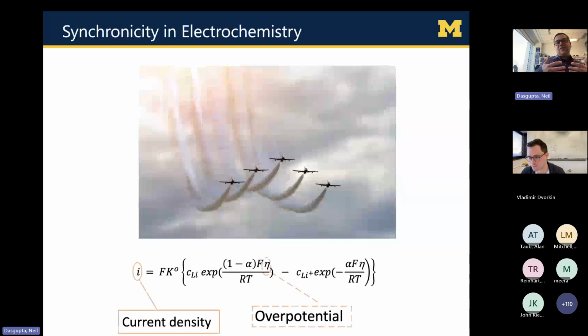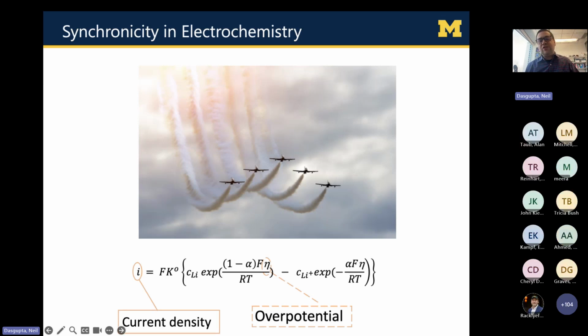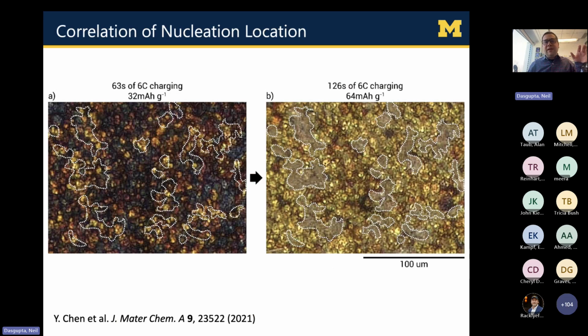And this actually makes us start to think about this concept of synchronicity in electrochemistry. So just like the synchronized swimming in the Olympics, you see people practice so hard to be able to move all at the same time. If we look at our Butler-Volmer expression from electrochemistry, the current density, which is what increases when you charge fast, has this relationship with overpotential. And normally we think of these as singular scalar quantities, right? Like there's a number for current density and a number for overpotential. But in reality, what we see is when we go to these fast charging conditions, some particles have a lower overpotential, other particles have a higher overpotential, and so some of them lithiate and charge much faster than others.